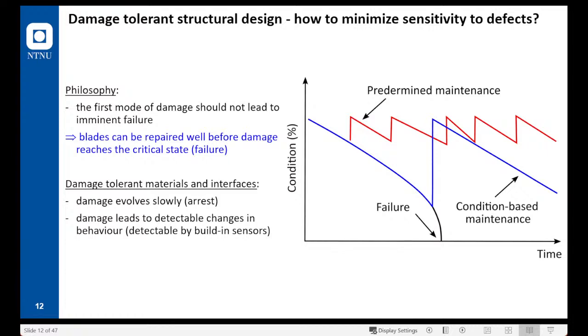Today, how damage is anticipated in practice is that, as I plot here on the x-axis, we have the time, and here is the condition of the blade. At predefined time intervals, now we follow the red thick line. At predefined time intervals, we inspect the blade, and then we can assess the damage. If it is non-critical, we don't do anything. If the damage is critical, we can decide if a repair is necessary or the blade cannot be repaired and is discarded. This happens every year at least, and it's a very time-consuming process.